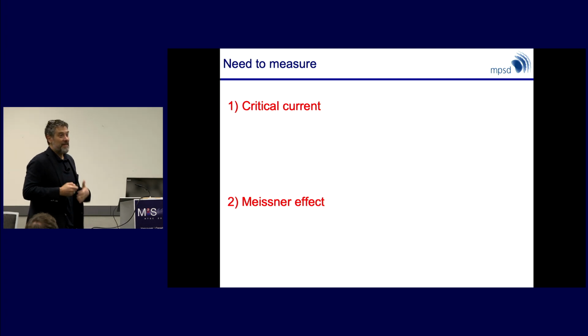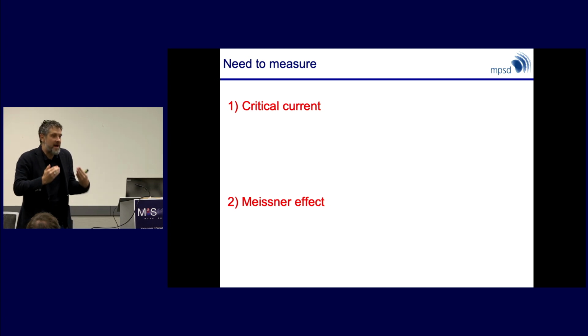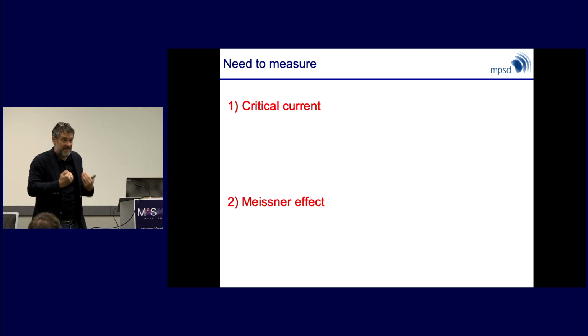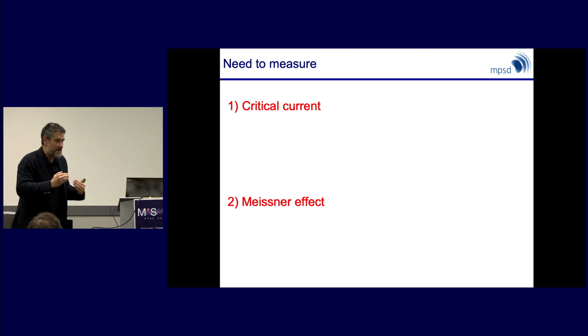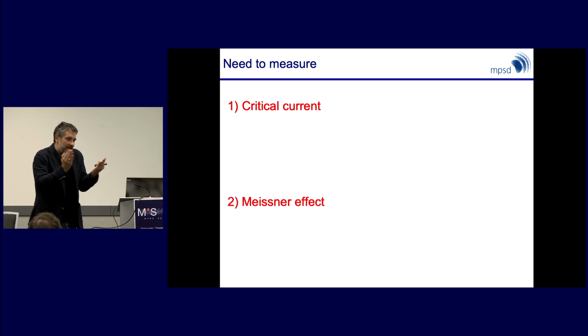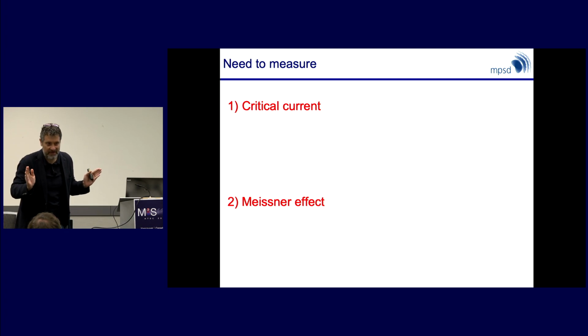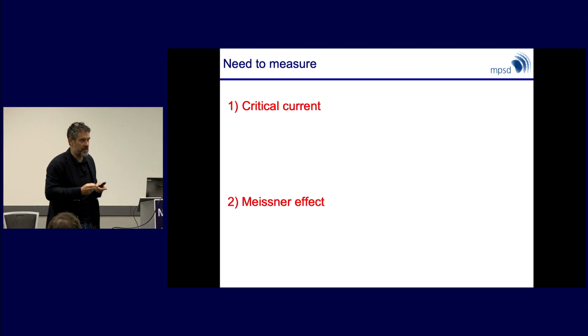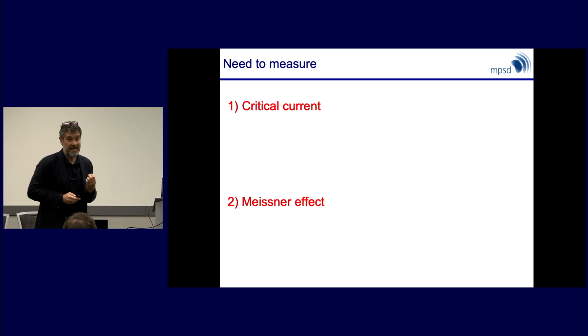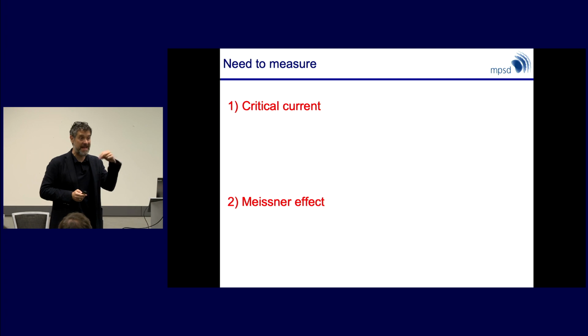As you have seen, those of you that were in the previous session, there's only so much that you can extract from fitting sigma 1 and sigma 2. And at the end of the day, it's unsatisfactory, you only can get partial things. And if you change the parameters of the fit, you could get different results. So you fit it, you cross your fingers, and you hope that you've done everything right, and you just report it. But what you really would like to see are the same features that you observed in equilibrium in true superconducting states on the ultra-fast time scales.